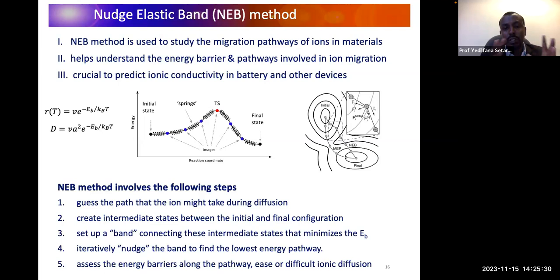This is implemented in GPAW, in Quantum ESPRESSO, as well as in VASP, which helps you understand or estimate the energy barrier of the path that you consider within the materials. So it's very crucial to predict the ionic conductivity. If you really know the energy barrier, the minimum or threshold energy required to diffuse one ion from the initial state to the final state, that gives you the idea of the conductivity.